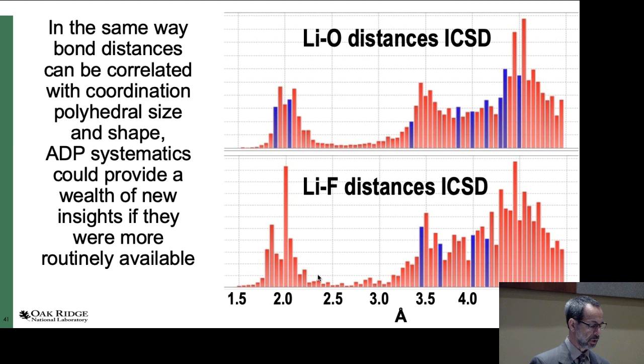So what I'd like to argue is that in the same way bond distances can be correlated with coordination polyhedral size and shape, here showing some systematics of lithium oxygen, lithium fluoride distances from the Inorganic Crystal Structure Database, ADP systematics could also provide a wealth of new insights if they were more routinely available.